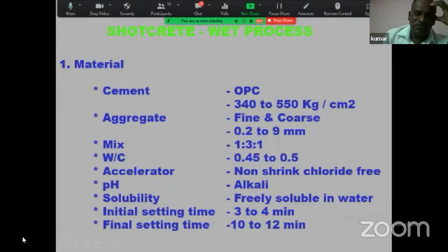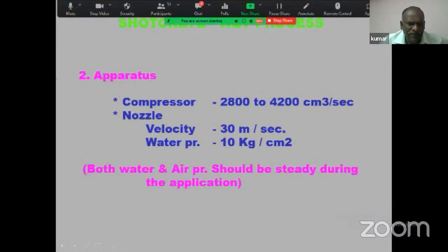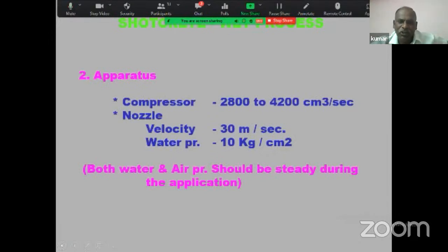So these are the specifications: cement, aggregate, and mix 1:3:1, and water cement ratio 0.45, 0.5. Accelerators, non-shrink chloride-free accelerator, that is for curing. pH should be alkaline, solubility has to be freely soluble in water, the initial setting time 3 to 4 minutes, because we are adding the accelerator, then final setting time 10 to 12 minutes. Then the apparatus, you can have a compressor and the nozzle velocity 30 meters per second, water pressure is 10 kg per centimeter square. We have to apply over there.